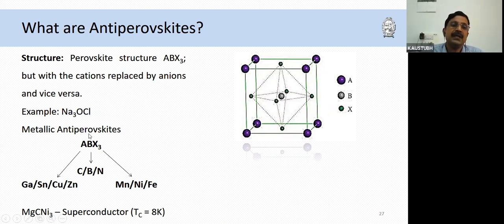Now, what we are talking about is something known as the metallic antiperovskites, wherein the A site is an element from the main group like gallium, tin, copper, or zinc, and the B site is a non-metal like carbon or nitrogen, and the X site is a transition metal like manganese or nickel. And a famous example is MgCNi3, which was found to be superconducting at around 8 Kelvin. So this is the structure of the perovskite or inverted perovskite or antiperovskite. Now if I say manganese in our case, then the manganese is sitting at this face-centered position. So obviously manganese will be in this triangular lattice.